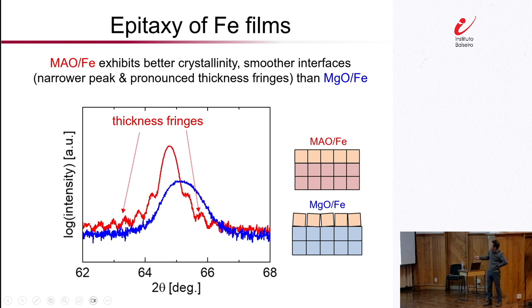So these thickness fringes are what often get film growth people very, very excited. This is a nice indication that we have very flat and smooth surfaces, both on top and the bottom of the film. These fringes arise because we have parallel X-ray beams reflecting off coherently from the top and bottom. So what you are seeing here is a series of destructive and constructive interferences from the top and bottom of the iron film. Okay, so all this is to say that this already suggests that iron on MAO gives us a much better crystalline quality.